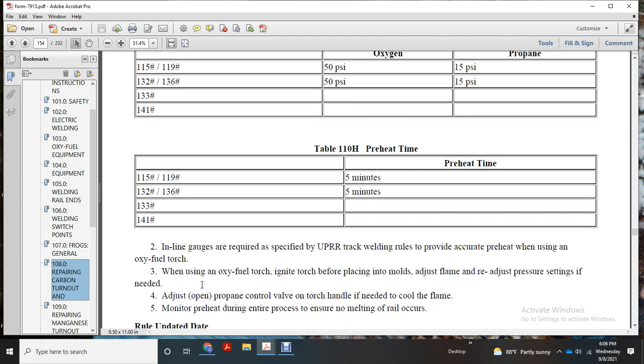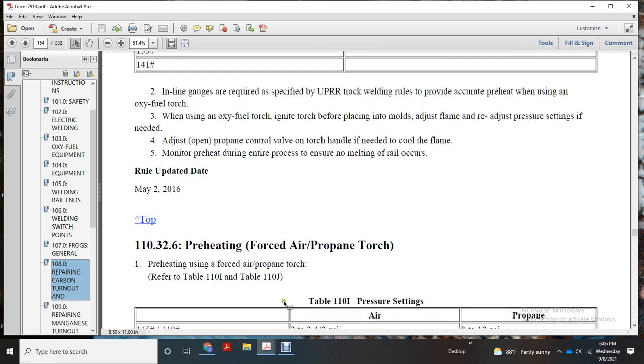In-line gauges are required, as specified in the Union Pacific Railroad track welding rules, to provide accurate preheating when using an oxy-fuel torch. When using an oxy-fuel torch, ignite the torch before placing it into the mold. Adjust the flame. Readjust the pressure setting if needed. Adjust the opening of the propane control valve on the torch handle if needed to cool the flame. Monitor preheating during the entire process to ensure that no melting of the rail occurs.